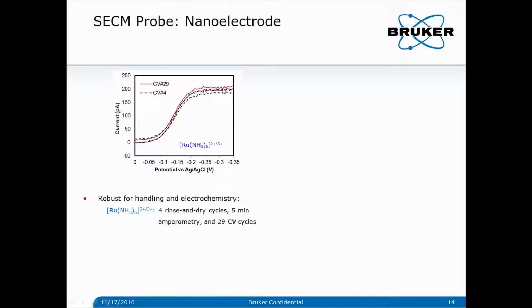We're showing 2 CV curves here. These 2 CV curves result from before and after a sequential handling and EC test. This handling and EC test includes, for example, 4 rinse and dry cycles, 5 minutes of amperometry, and 29 CV cycles. From the comparison here, no degradation in EC performance is observed.